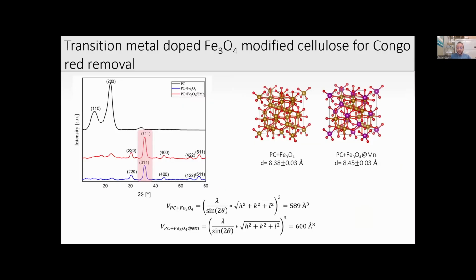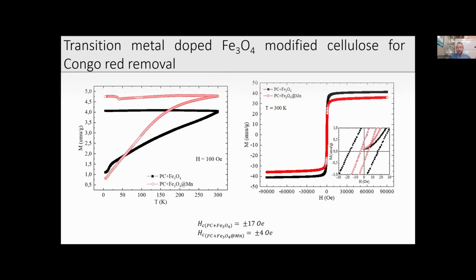The XRD analysis proved the presence of manganese and the partial substitution of manganese inside the structure of magnetite, which led to the increase in the volume of the structure. But as far as the magnetic property is concerned, we can observe on the left side the magnetic field against the temperature, and this novel material appears to show a blocking temperature higher than 300 Kelvin. And since there are no peaks in the field cooled, zero field cooled curves, it is possible to state that this material resembles the behavior of a paramagnetic material, while on the right side, it is proved that the coercive field is really low, near to zero, about 4 Oersted for the pulp cellulose modified with the magnetite doped with manganese.